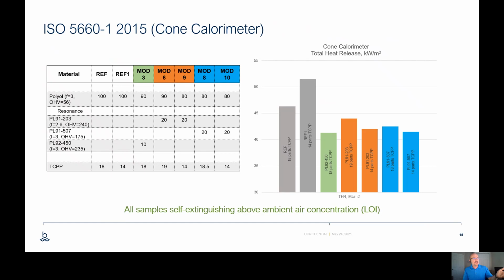The first reference is at 18 parts of TCPP. The second reference is at 14 parts of TCPP. Not only did we have splitting with those materials, but you can see the reaction to fire decreased. In other words, it got worse at the 25 kilowatt per square meter heat flux. The PL92-450, introducing it into the formulation at 10 parts, automatically began to improve versus 18 parts of TCPP in the reference.